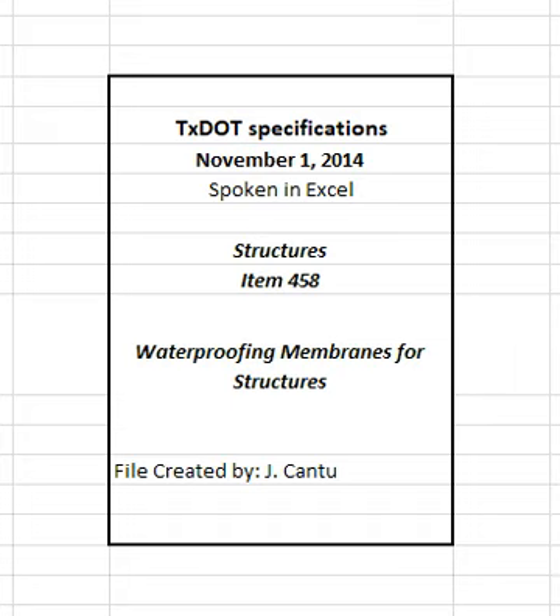Apply the primer and waterproofing membrane board panels only when the substrate temperature is above 50 degrees Fahrenheit. Seal joints by centering 6 inches gusset tape over the joint and pressing firmly into position. Roll in the panels and jointing tape with sufficient pressure to assure maximum adhesion, conformance to substrate, and elimination of air bubbles. Follow the manufacturer's recommendations for installation. Begin backfilling as soon as the application of the waterproofing is complete. Complete backfilling within 48 hours after the waterproofing material is applied to a non-horizontal surface.